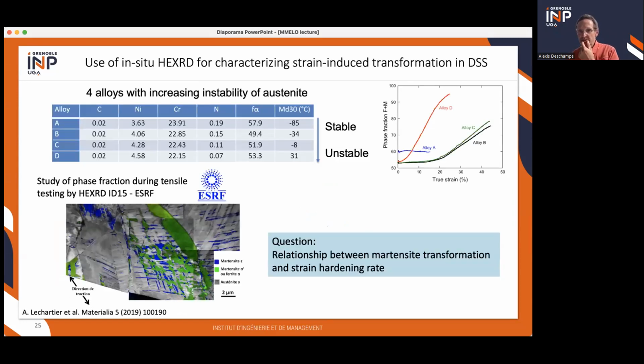To continue on this TRIP effect, we can see later on, it's not on the same material, it's in a duplex stainless steel, but the principle is the same. You can follow what happens in situ during deformation, and not in situ during heat treatment. And the question then is to be able to characterize the phase transformation due to strain and relate that to the mechanical properties and especially the strain hardening rate.